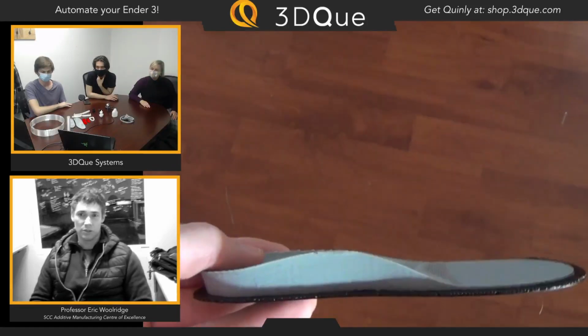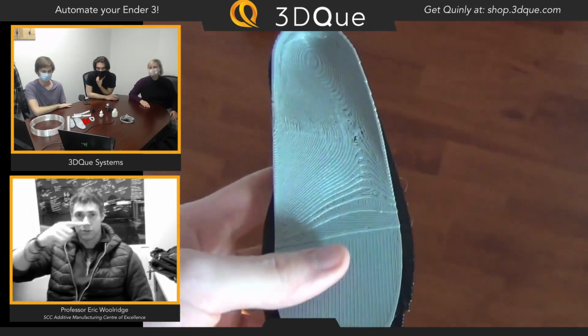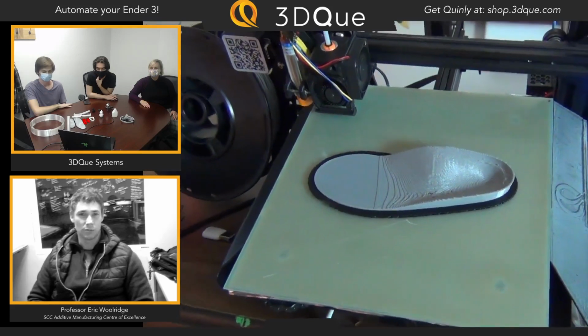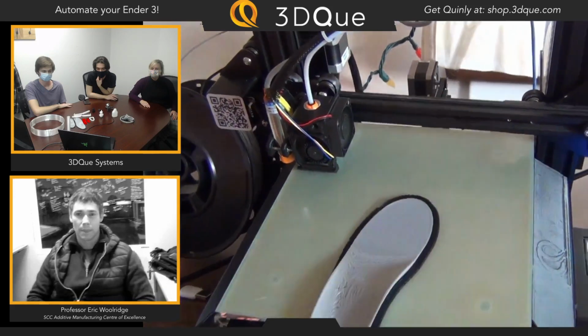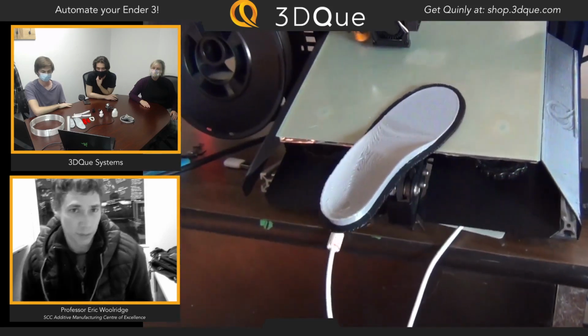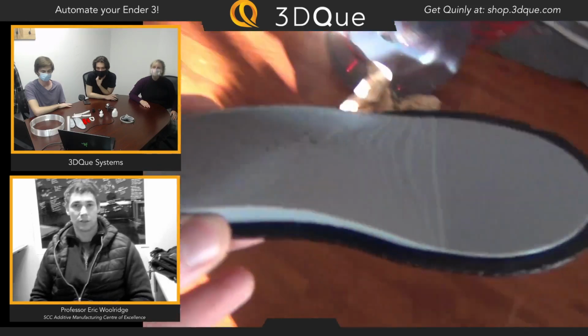Biggest problem with TPU that we see is as it gets taller and thinner, that wobble, your actual friction associated with your extruder pulling that bead along, can shift it out of whack. So you can get a little stuff there. We do try to do pretty good compression on it, depending on what kind of driver system we're using to push it down. But we actually have probably a pretty high success rate with TPU. But we're also not trying to do any kind of crazy shapes either. We're usually doing things that are cylindrical or grip-like in their nature.